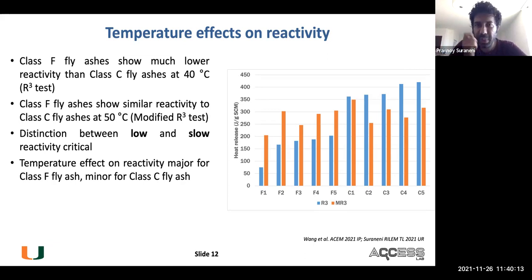You want to distinguish between materials which have low reactivity and materials which have slow reactivity, right? Because something could be reacting very slowly, but if it's reacting in a sustained manner, that's not a bad thing. If something is reacting very little, but it's not continually increasing with time, that's not so useful. It gets a little subjective, of course, but you really want to consider reaction kinetics very carefully, especially for materials which are slowly reacting.